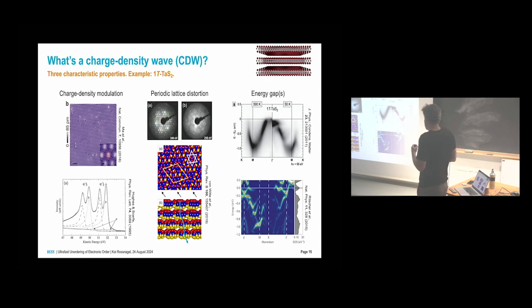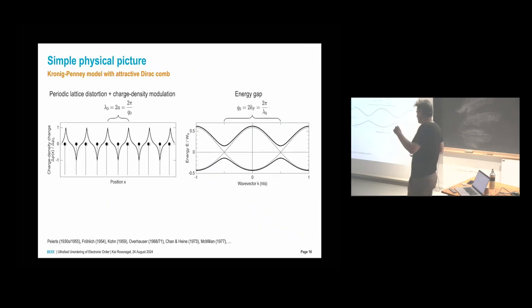and as they are illustrated in textbooks. For example, using this simple Peierls-type model, which a simple-minded experimentalist like me can also deal with. So in this model, you can see it. You have an attractive Dirac comb potential, but this means that here you have not such a nice-looking sine wave charge density wave, but still you have a periodic modulation of your charge density, and also your atoms are moved with the characteristic wavelength here with double the periodicity.